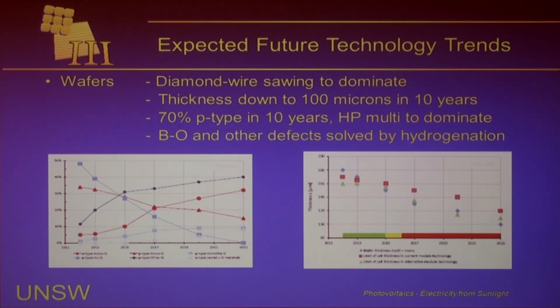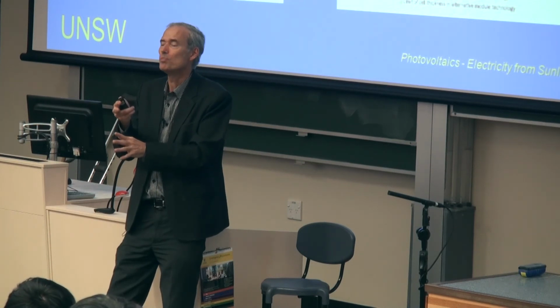dominate in the future. Now, if it does, that will make it hard for the UMG silicon producers, because people making the high-performance multi don't want the UMG silicon. There's too many impurities in there. And if you get all those impurities into the grain boundaries, it's very hard for the hydrogen to passivate contaminants and defects at the grain boundaries themselves. Okay, the hydrogen passivation technology seems to do a good job on the crystalline regions, but not necessarily a good job at contaminants that are located in the grain boundaries.